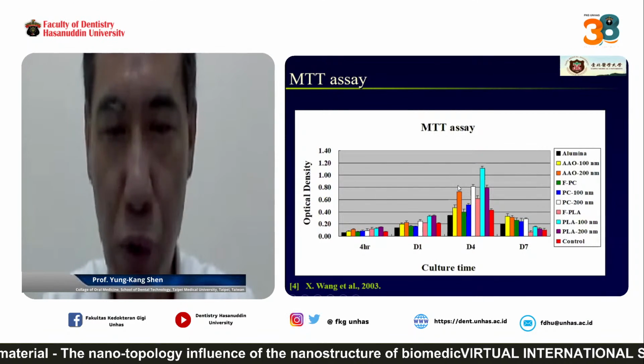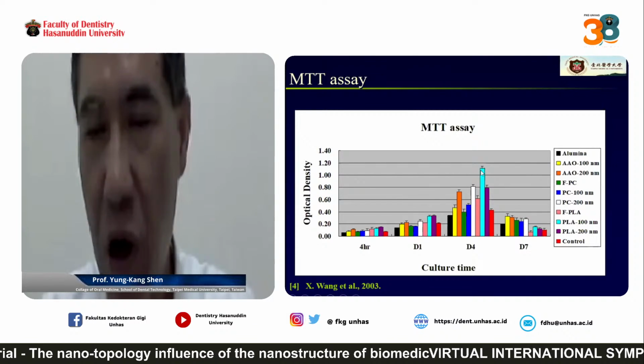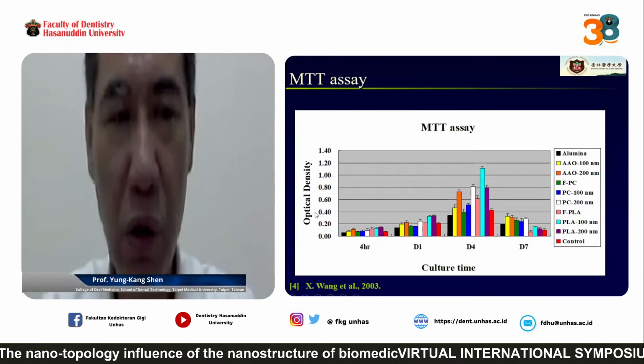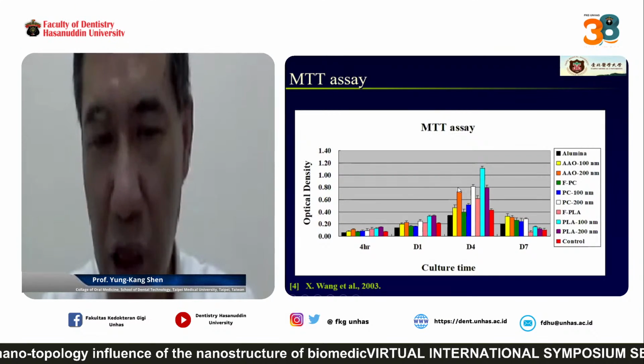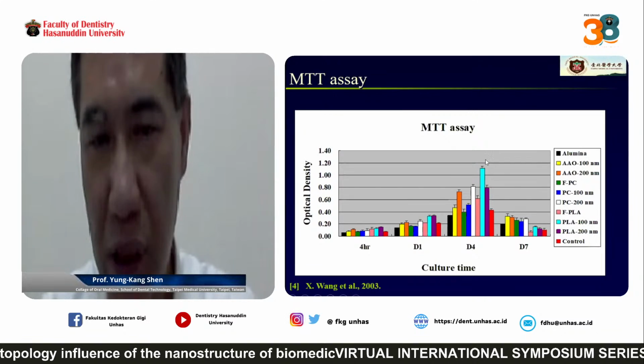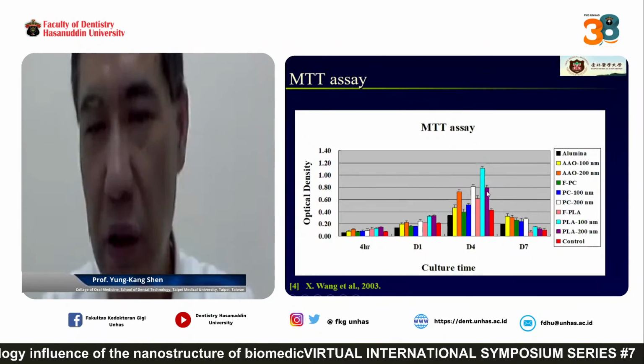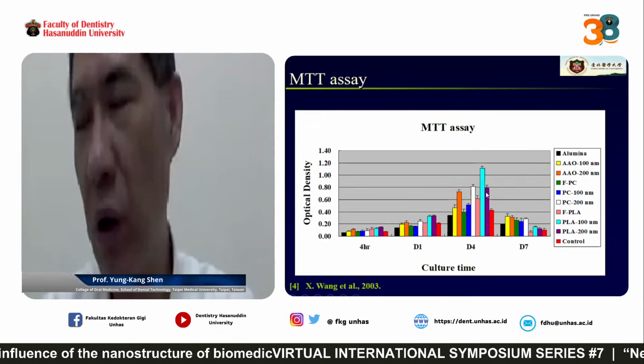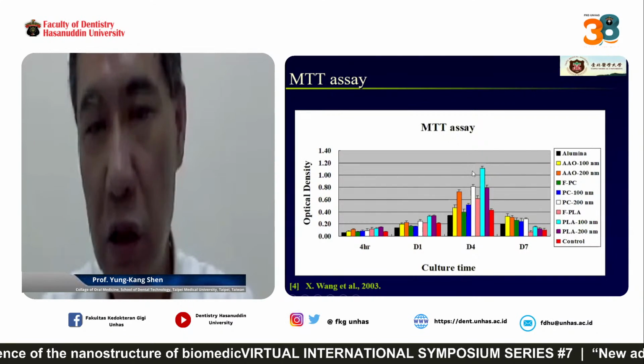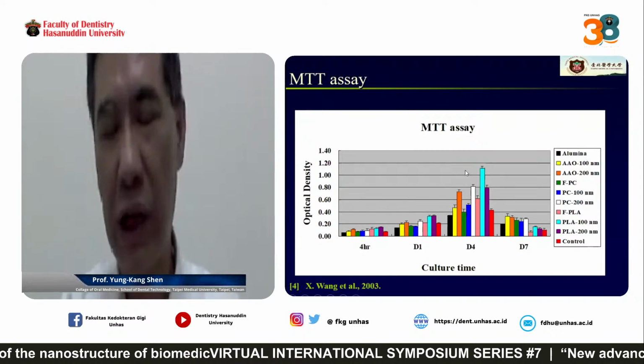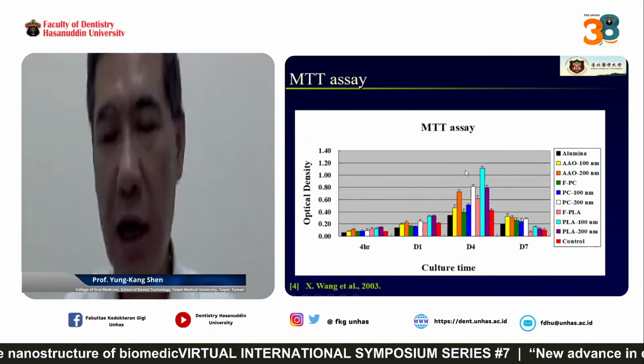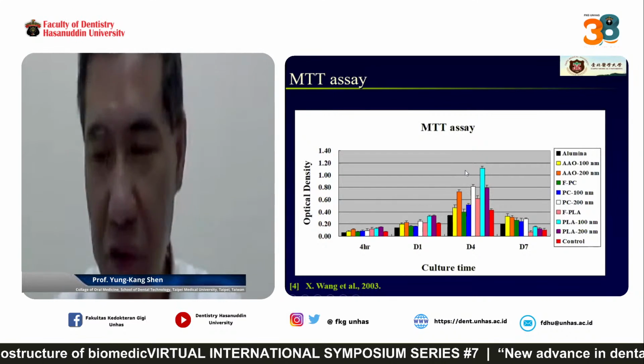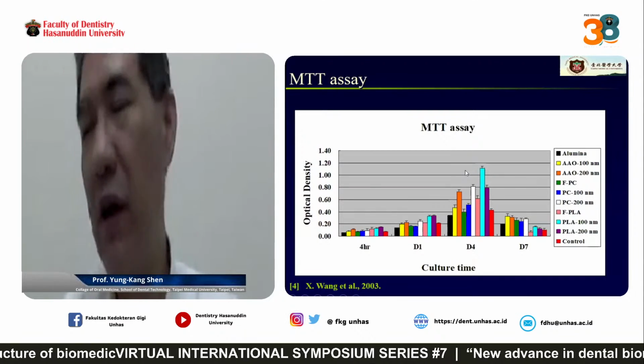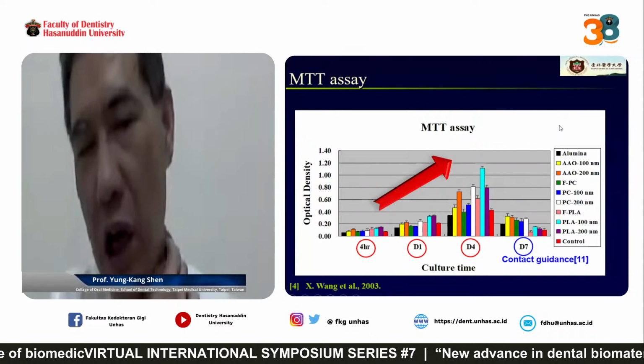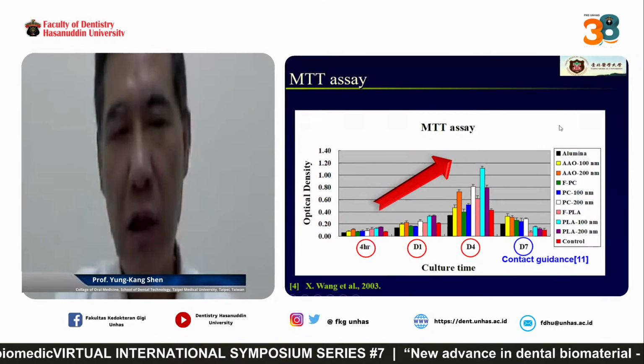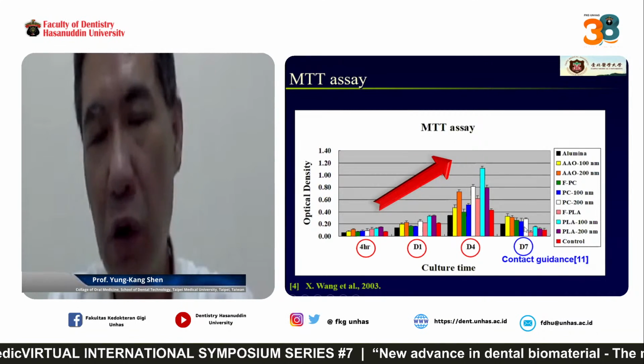You can see from 4 hours to day 4, this is the PLA for 100 nanometer. We can get an optical maximum OD value here. And we can make a comparison for day 4. Here, you can see when you use the nanostructure, they all can get a very good MTT value compared to the flat thin film. So we can also see, if you want to do cell culture, flat thin film is not good. The thin film with the nanostructure is better for growing the cell culture. You can see from 4 hours to day 4, the OD value also increases. For day 7, maybe we must change the medium.